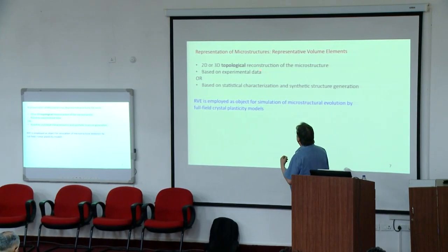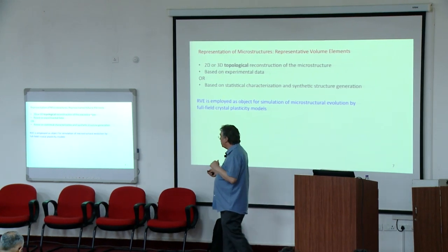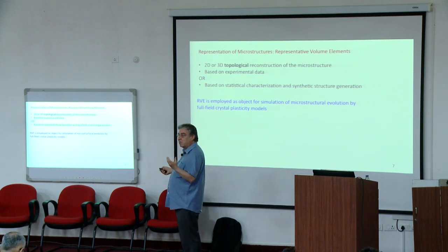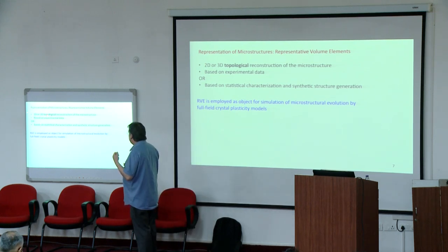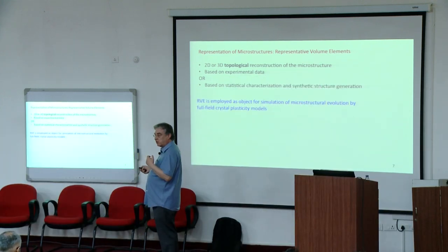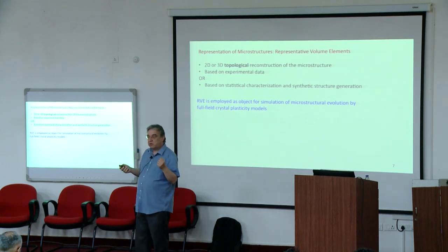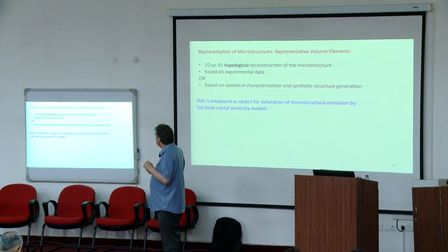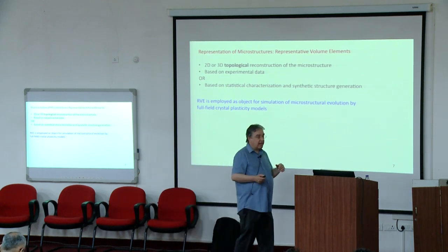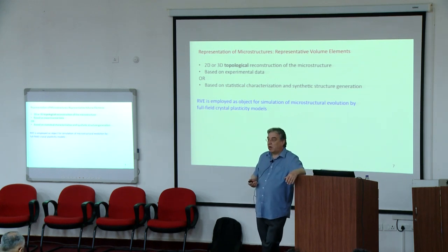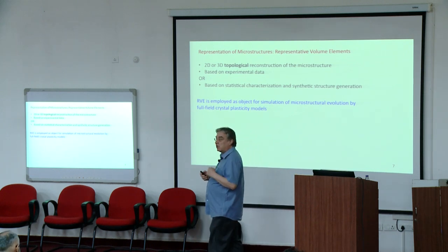So as I said, before we go to statistical methods, I want to expand a little bit on representing microstructures by what are called representative volume elements. These are 2D or 3D topological reconstructions of the microstructure. Topological means spatially distributed, taking into account the neighborhoods of the grains. And this may be based on experimental data. If you want to do it in 3D, then it's really a lot of work to have a 3D picture of a metallic microstructure. You can do it with synchrotron radiation, for example, or you can do 3D microscopy by slicing and viewing different layers in a material, but that's time consuming and very costly. So it's not very easy.